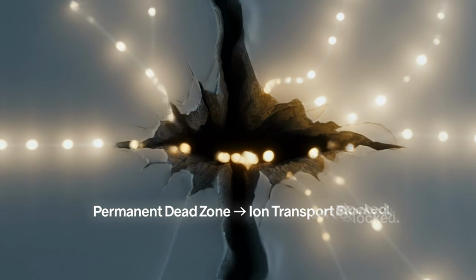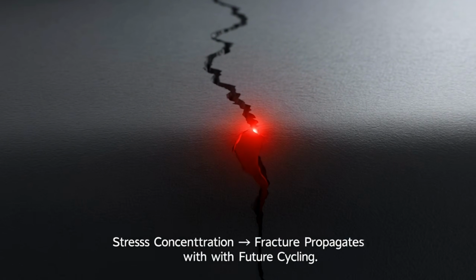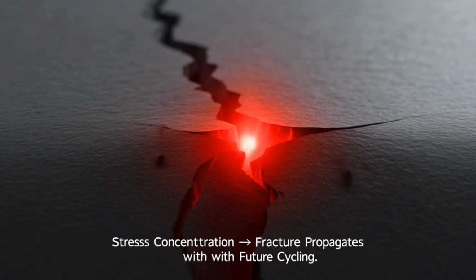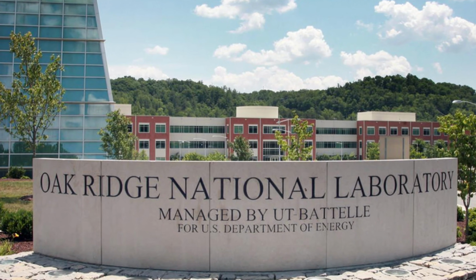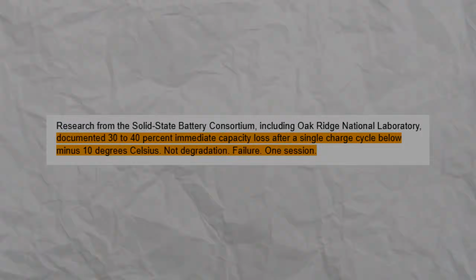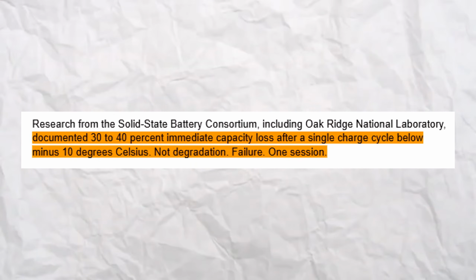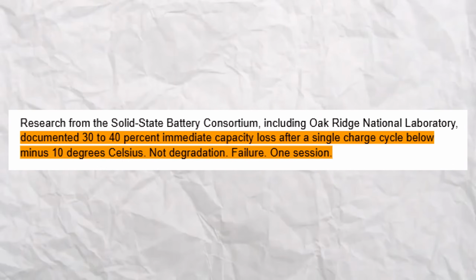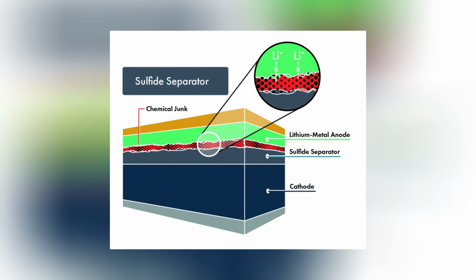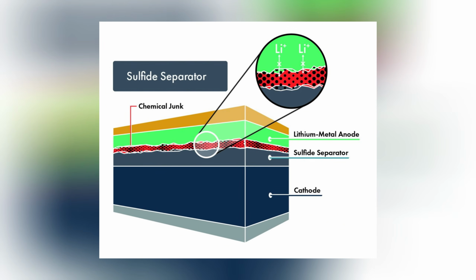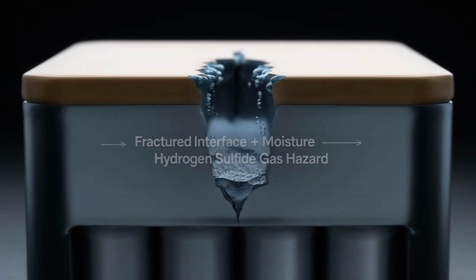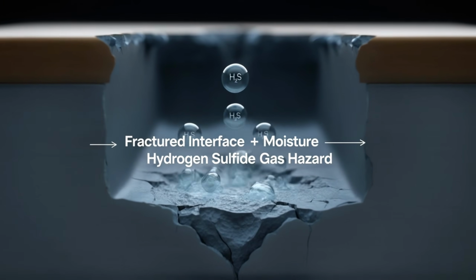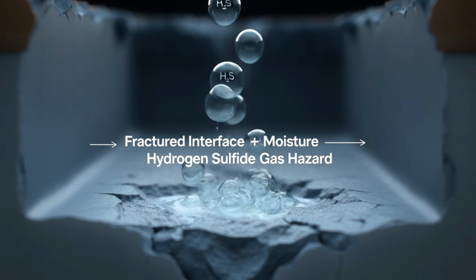The crack creates a permanent dead zone where ions can no longer transport efficiently, and a stress concentration point where future cycling will keep propagating the fracture. Research from the Solid-State Battery Consortium, including Oak Ridge National Laboratory, documented 30 to 40% immediate capacity loss after a single charge cycle below -10 degrees Celsius. Not degradation. Failure. One session. Fractured sulfide electrolyte also introduces a chemical hazard. If the cell's hermetic seal is later compromised, the fractured interface can react with moisture and produce hydrogen sulfide gas. This has been documented in real-world failure analysis.